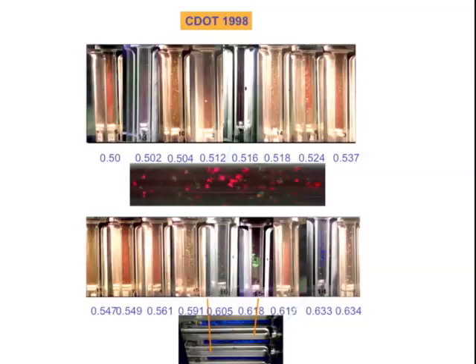The main thing we found in this experiment is when you look at all these volume fractions up through random close packing, but not above, because you can't get a sample that's disordered above there, everything crystallizes. And it crystallizes essentially immediately. So after this experiment, not only did everybody sort of agree that this was okay, and people that tried to do density matching on the ground, I'll get to that in a second, didn't do very much. But after this experiment, all the theories agreed and all the simulations agreed that there's no glass phase. So now it's accepted that for monodispersed hard spheres, you have a liquid and you have a crystal, but you don't have a glass.